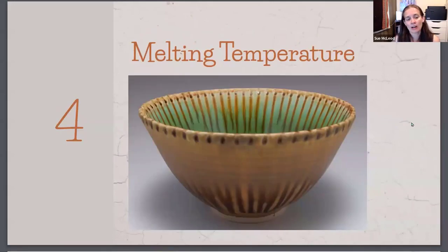Melting temperature can be increased or decreased by either adding more flux or boron to lower melting temperature, and we can add silica and alumina to increase melting temperature. So there's different ways to go about changing melting temperature, but basically we're replacing high melting temperature materials with low, or vice versa, depending on the direction that we want to take.